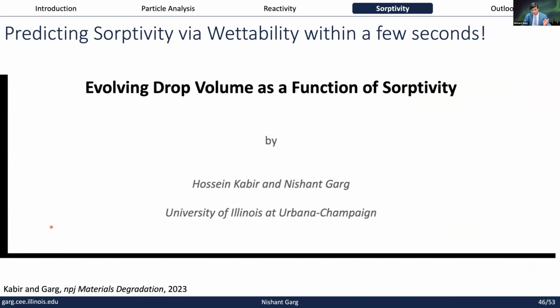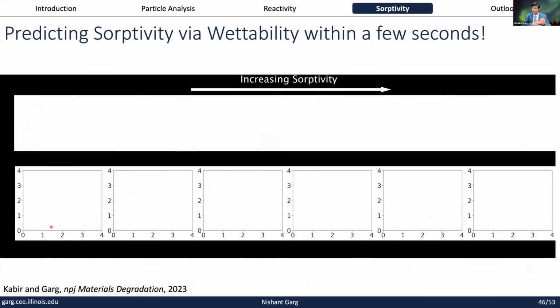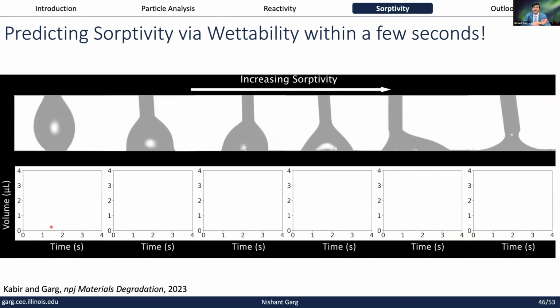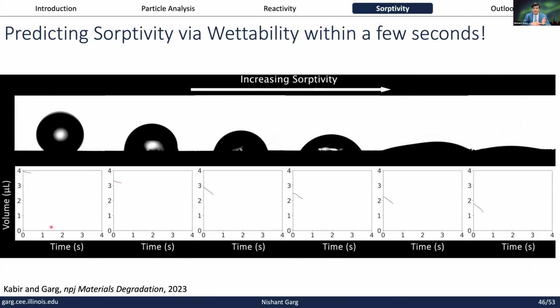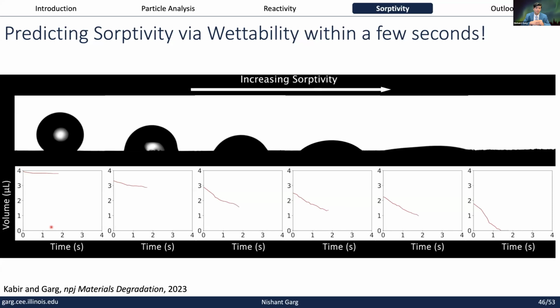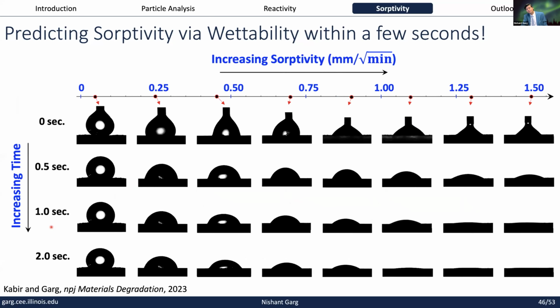So here's a small video that we put together, which shows how the drop volume and its change is very well in alignment with the sorptivity of the sample. From left to right, you have samples of increasing sorptivity, and you can see the droplet dynamics changes quite a bit. Again, here's another snapshot where we can see that just in a few seconds, even before you officially drop it, the droplet starts to be sucked in by the substrate, because it's kind of hungry for that droplet.